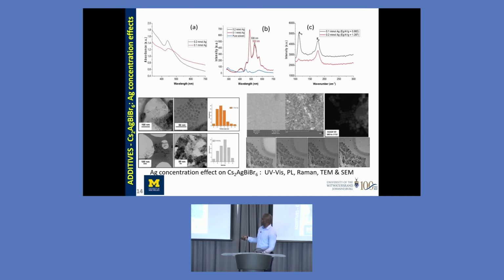Furthermore, with higher concentration in this specific case, 0.2 millimole, you could see that there's some agglomeration. And agglomeration means that we might not be able to proceed further with our characterization. Hence, we focus on the smaller concentration. We made the film with the smaller concentration, and one could see that there are some big crystals.